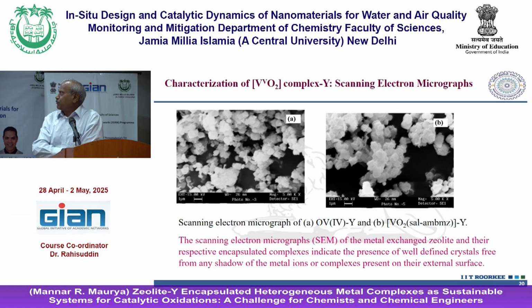Now see characterization, scanning electron microscopy. Whenever you do this, when you have only metal ion exchange, you will find the surface not crystalline in nature because part of the metal ions are present there. Okay, maybe on the surface, inside the surface you will find not very good. But once the metal complex has formed and it is washed very nicely and thoroughly to remove any metal and metal complex from the surface, you will see the sharpness in the crystalline nature of that zeolite. That gives the feeling that the crystallinity of the zeolite is still maintained after encapsulation of the metal complex. Only that much information your morphology can give.